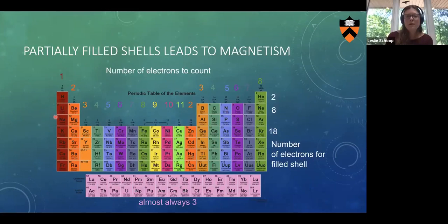However, we know we do have magnetism. And so if you are in the d-block, then you can have open shell systems. Here it is important to differentiate between two types of open shell systems: localized ones, where the spins are localized and so can contribute to magnetism, and delocalized ones, which do not necessarily contribute to magnetism, but rather to metallic conductivity.